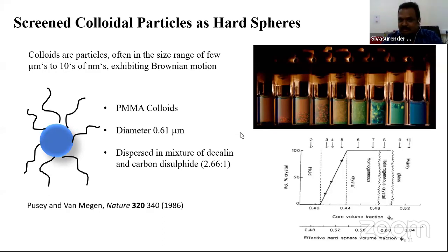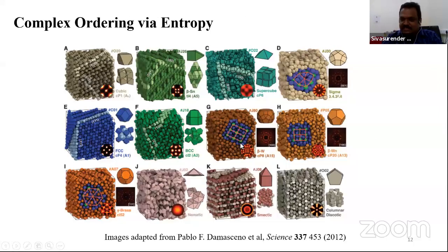And not only that, entropy can form this crystallization, and much more complex and rich ordered phases can be formed by just controlling entropy, for example, by changing the shapes of the colloids, as shown here, and you can get different kinds of order. So essentially, this is up to your dream, what kind of particles you synthesize, and you synthesize them in such a way that you remove the energetic interaction. Then entropy allows you to get a rich range of order in materials.